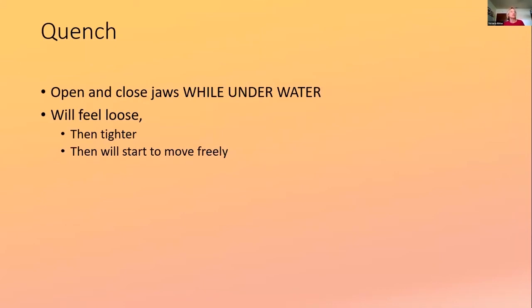While you're quenching, open and close the jaws. I like to get it started before I hit the water. And then as you're in the water, you're going to feel them get loose initially, but then tighter, like to the point where you're like, oh shoot, this isn't going to work. But if you keep moving them open and close, they will start to move freely. And then you'll be all set.